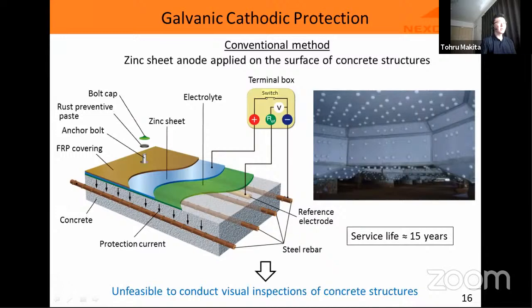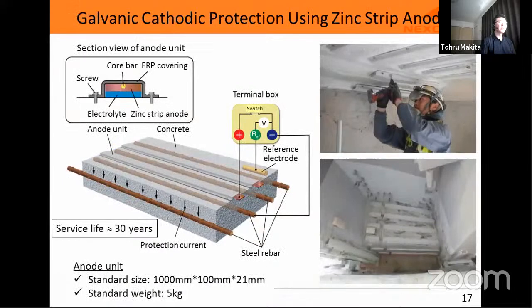But because the concrete surface is covered by zinc sheet anode, it is not possible to visually inspect the concrete structures. In order to make the visual inspection possible, a new galvanic cathodic protection system using zinc strip anode was developed. In this system, zinc strip anode is discretely applied on the surface of concrete structures, and the entire surface of the concrete structure is not covered by zinc anode, so it is possible to visually check the condition of the concrete structure.